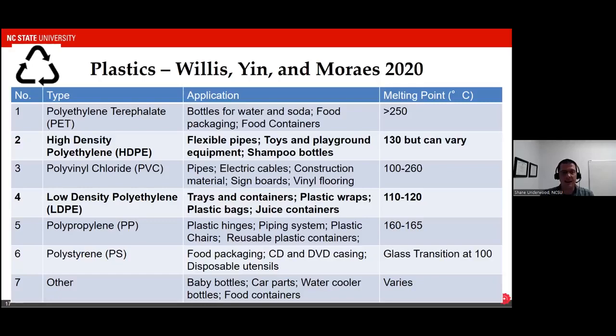In the US, at least, the recycling rate for high density polyethylene is around 27%. So of all the high density polyethylene we produce or use here, we only recycle less than a third of that material. In the case of low density polyethylene, it's significantly lower. Here, low density polyethylene is recycled at a rate of about 6%.